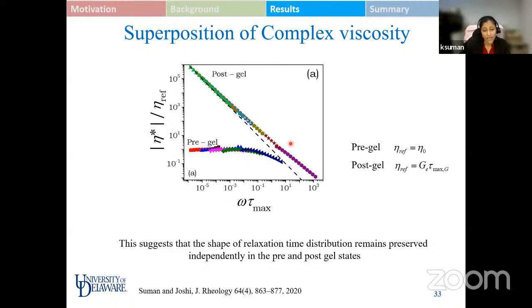The very fact that it gets superposed very nicely suggests that the shape of the relaxation time spectrum remains preserved independently in the pre-gel state and the post-gel state, due to which we are able to get a very nice superposition over here. So now the power of rheology is that by doing a simple experiment in a narrow window of frequency, we are able to get data in a wide range of frequency by doing a superposition over here.